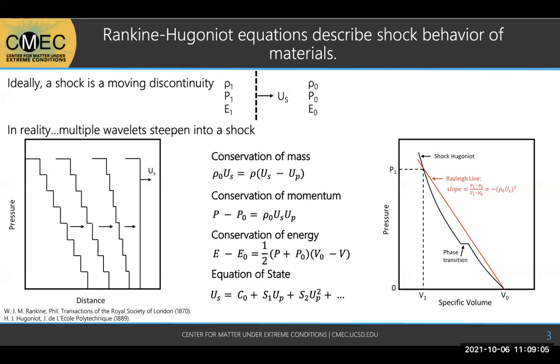And so Rankine and Hugoniot, in the 1800s, developed this system of equations that can be used to solve for the pressure, temperature, and volume relationship based on a shock. The resultant PV relationship is called the Hugoniot, which is the black curve in that graph, where little blips are generally evidence of phase transitions. The Hugoniot is also importantly not the path followed from the passing of a shockwave. It's just a locus of the possible end states. The actual path followed from a shockwave is called the Rayleigh line, and that's the red bisector. Next slide.